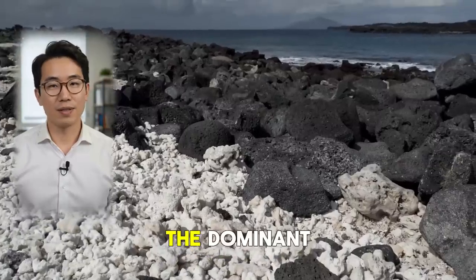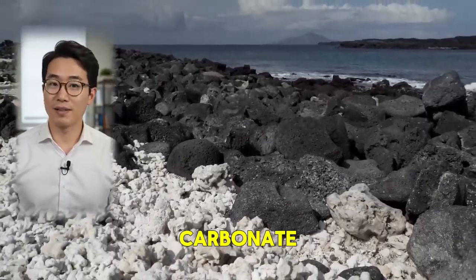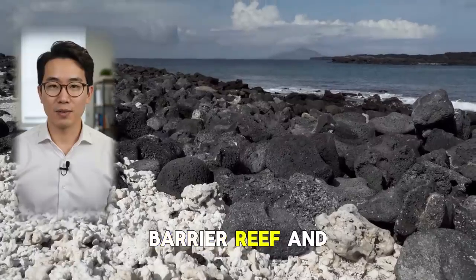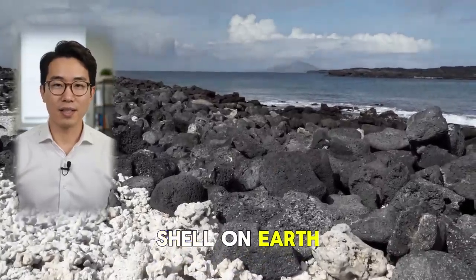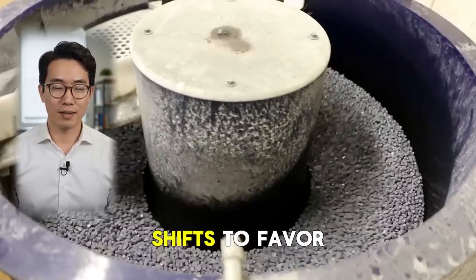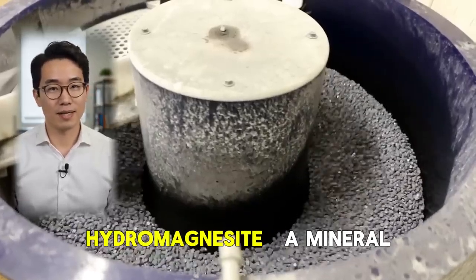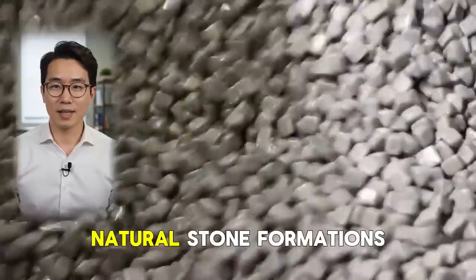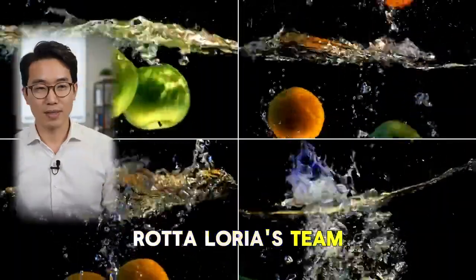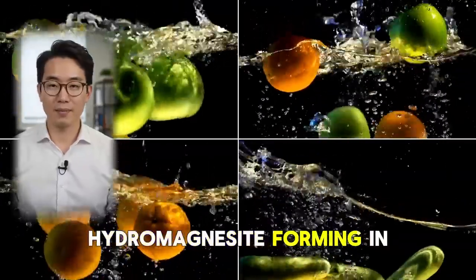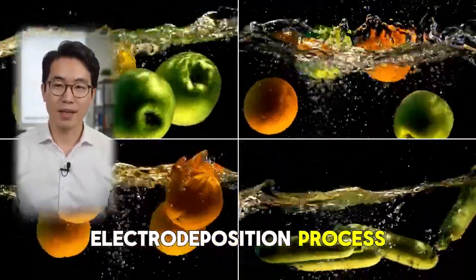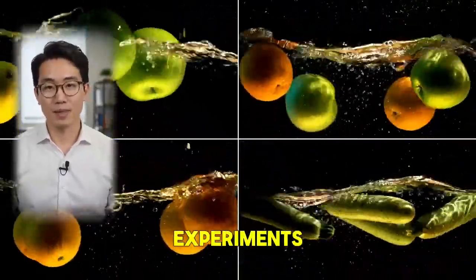At 2 to 3 volts, the dominant deposit is calcium carbonate, the same mineral that forms the Great Barrier Reef and every oyster shell on Earth. At around 4 volts, the reaction shifts to favor magnesium hydroxide and hydromagnesite, a mineral found widely in natural stone formations. Rotta Loria's team was the first to document hydromagnesite forming in this electrodeposition process. No one had seen it before in similar experiments.